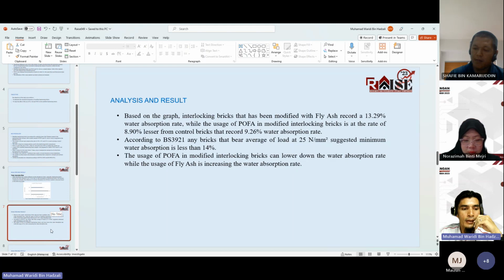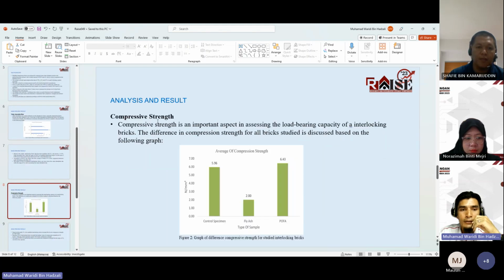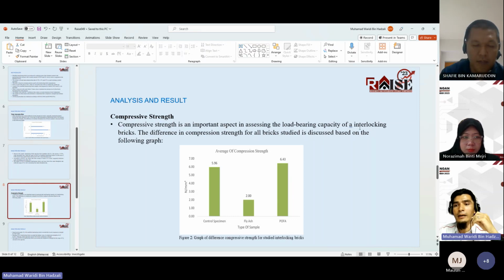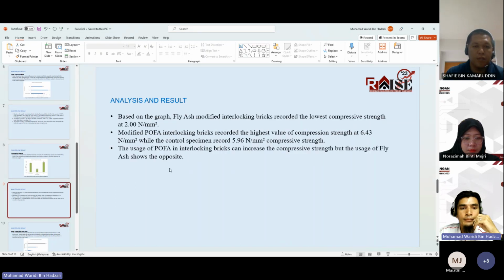So POFA bricks record the lowest water absorption rate. Next, the compressive strength. Compressive strength is an important aspect for the load bearing capacity of a brick. Based on the graph, the highest compressive strength is recorded by the POFA brick, and the lowest is the fly ash brick. So from the result, we know that POFA has the highest strength compared to the other bricks.